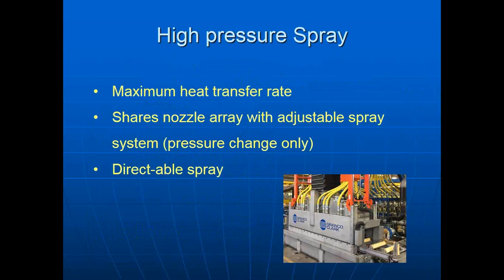Finally, the highest performance system is high pressure or high impact velocity spray. Here, the water droplets are accelerated fast enough that they affect the steam barrier that forms around the part and provide the maximum heat transfer rate that's available.